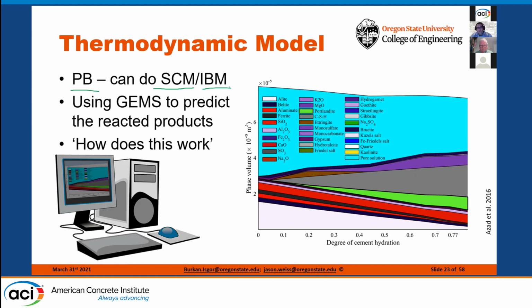And what we want to do here is get into a little bit of how this works. Right, so a lot of the early work here was done by EMPA, which is a Swiss group, and Barbara Lothenbach's group. But what you'll see here is this has striking similarities to what Powers and Brownyard were doing. So with no hydration, we have cement. Now here, cement is not just a big gray blob. It's essentially everything from this triangle on down. Because what we're going to do is consider all of the different components of the cement.